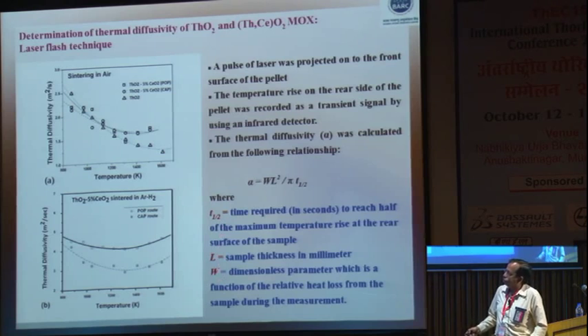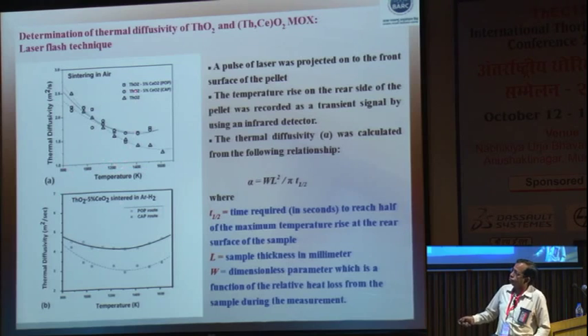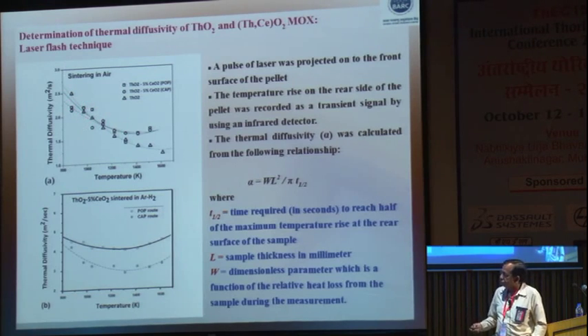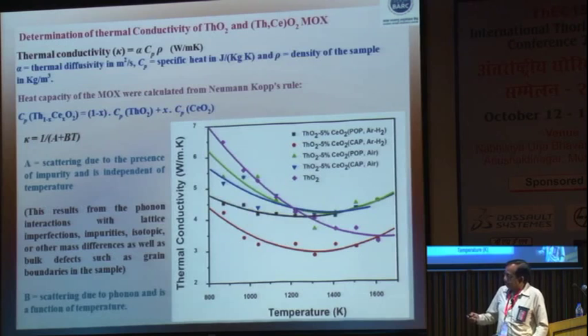So, using these three you can get the thermal diffusivity, which has been plotted here as a function of temperature for sintered in air product as well as sintered in argon and hydrogen. POP as well as CAP products have been done, and you can see slight differences, and that is because of the variation in porosity and density. So, this is all experimentally evaluated.